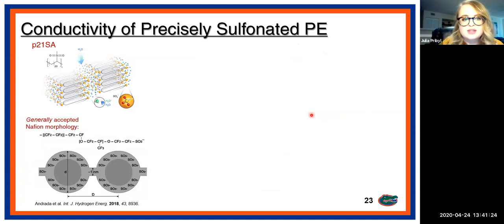So what they did then was compare this material to the benchmark ion transport material, which is Nafion. So this is kind of a general chemical structure of Nafion. It's a fluorinated polymer that has this sulfonate group on the end. And the secondary structure of Nafion is actually pretty widely debated even still. But generally, what we think in the scientific community is that there's these pores that are decorated with the SO3 minus groups that are connected by a system of very small channels. And then the ions have to take quite a torturous path to migrate their way through these type of disordered membranes, whereas the system that we're looking at is now highly ordered and decorated with these well-defined channels containing the sulfonic acid groups.